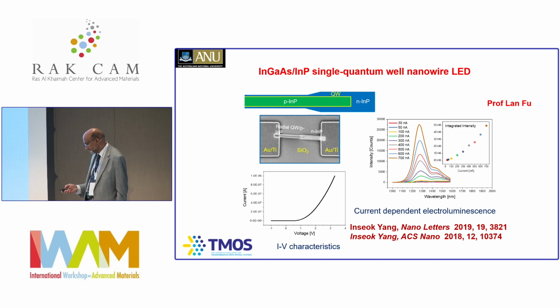It turns out that when you put in metals, they really absorb the light. That means you create huge losses in the cavity, a lossy cavity, so you have to pump it harder. If you pump it harder, you generate a lot of heat. That means the gain goes down, and you have to pump even harder. It becomes like a vicious circle. Another student is now replacing these metals with the transparent conducting oxide Kristen mentioned in her talk, so that we can minimize these losses.